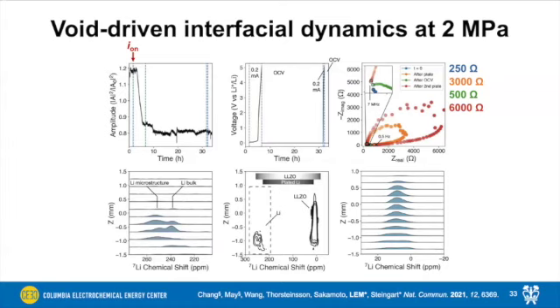So what we see here is that this peak corresponds to LLZO. But then at the interface, we have this large additional shoulder at much higher frequency. And this is very unusual. This higher frequency is way out of the range where we would expect normal lithium ion conductors to show up. It's actually heading towards where we would expect electronic conductors to show up. So I told you in the previous project, we actually had such a hard time distinguishing all of the different ion conductors that were present in our SEI layer because they all overlap with one another. And now we're getting good resolution.